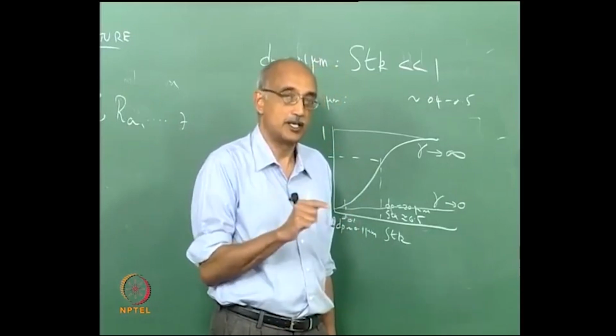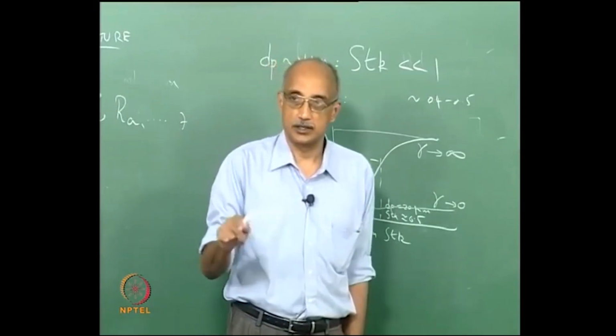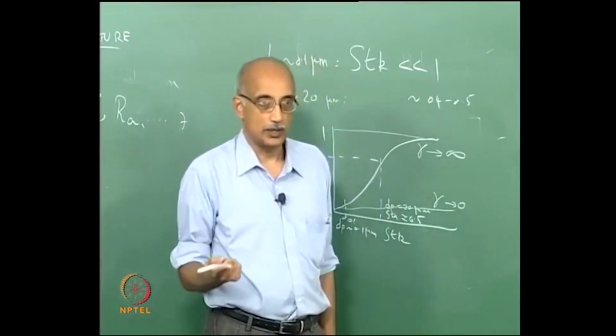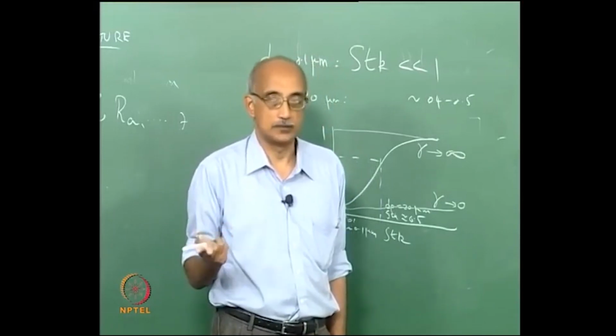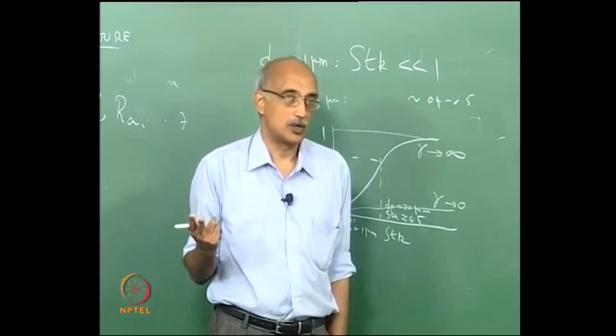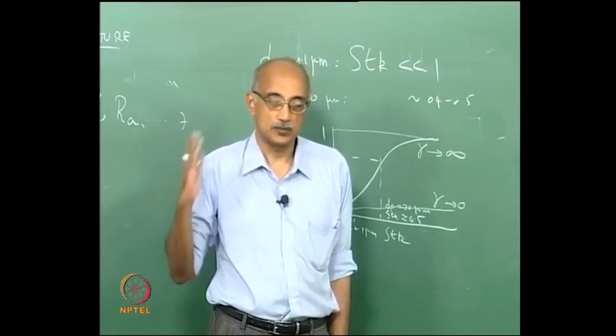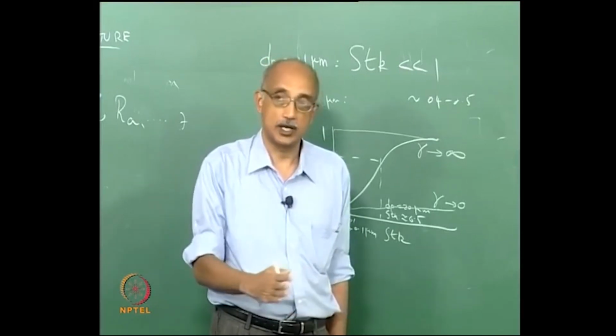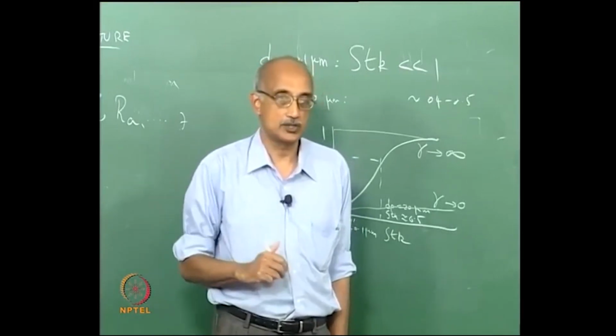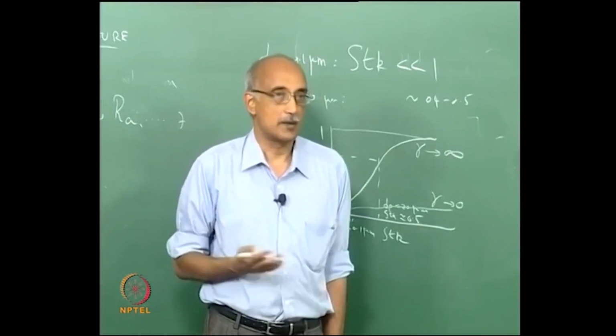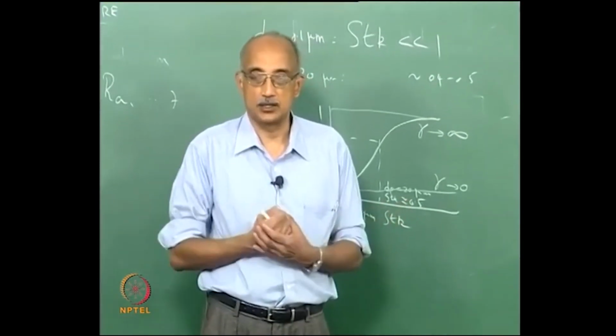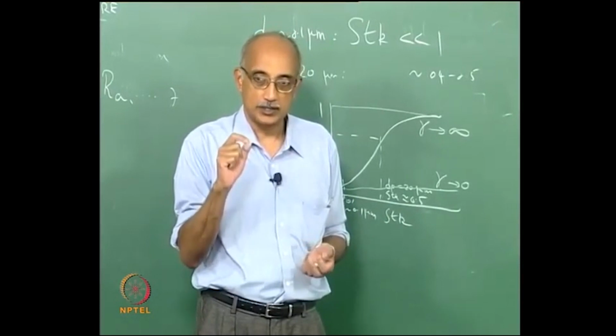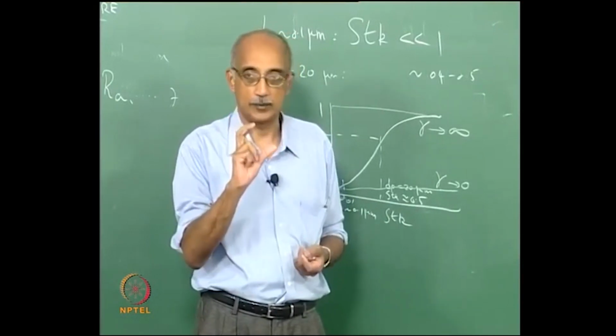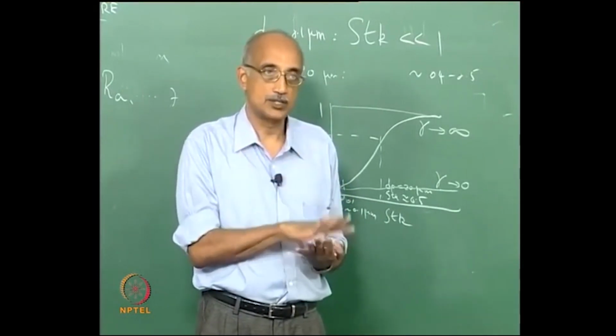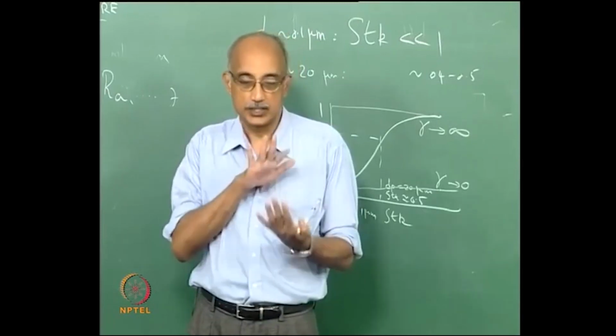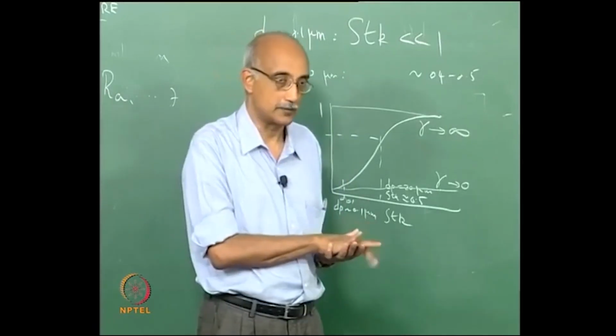Again, remember there are multiple mechanisms by which particles can degrade surfaces. Fouling is one, but there is also something called erosion. Erosion does not care about surface energy. In erosion, particles strike the surface at high velocity and cause physical damage to the substrate. It does not matter if it is a low energy or a high energy substrate. Surface energy only affects fouling, which is an adhesive phenomenon. It requires that particles stick to the surface. So, surface energy has a very direct effect on that.